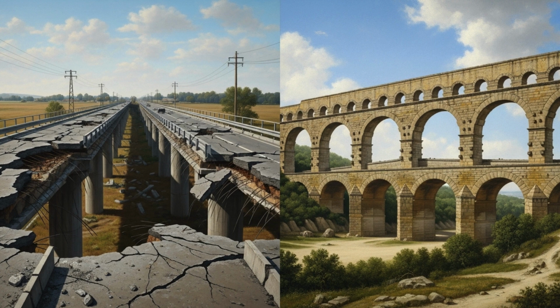And there's another massive problem. Portland cement production is an environmental disaster. The cement industry produces 8% of global CO2 emissions, more than the entire aviation industry. Why? Because making Portland cement requires heating limestone to 1,450 degrees Celsius. That requires enormous amounts of fossil fuel energy. Plus, the chemical reaction itself releases CO2 when limestone breaks down. For every ton of Portland cement produced, approximately 0.9 tons of CO2 are emitted. Roman concrete, made with lime burned at lower temperatures, used volcanic ash, a waste product, required far less energy, produced far fewer emissions, and lasted 20 times longer.